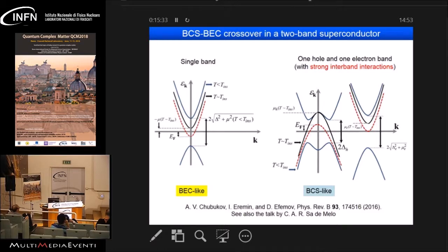And in the case of a single band, as you expected, you can have this kind of BEC-like state. So the minimum gap opens at k equals 0. However, in the case of these two-band systems with strong interband interactions, at least one of the bands shows a BCS-type electronic structure. So the gap opens at kF, not at k equals 0. So I think this may be relevant to our data, suggesting that if you have strong interactions between two bands, you may have a BCS-like state, even if we have a large delta over EF.